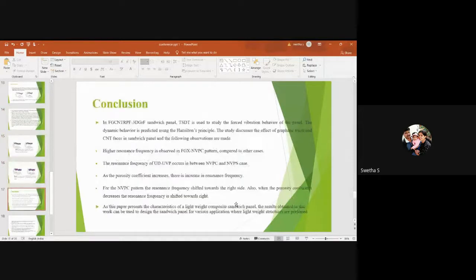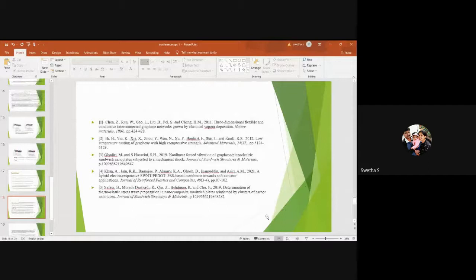Now, the conclusion of the study: the higher resonance frequency is observed in the FGX-NVPC pattern compared to the other cases. The resonance frequency of uniform varying porosity occurs between the NVPC and NVPS cases. As the porosity coefficient increases, there is an increase in resonance frequency. This is also observed. For the NVPC pattern, the resonance frequency shifted towards the right when the porosity coefficient decreases. As this paper presents the characteristics of lightweight composite sandwich panels, the results obtained can be used for the design of sandwich panels for various applications where lightweight sandwich structures are preferred. So these are my references.